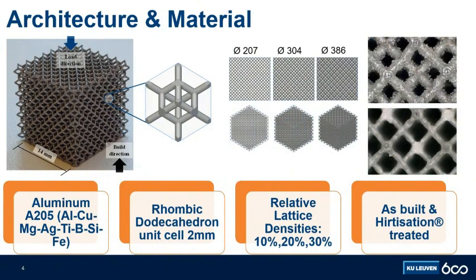For the architecture and the material, I have worked with aluminum A205. You can see the composition of the alloy on the screen. My main geometry was a rhombic dodecahedron unit cell of 2 millimeters, stacked horizontally and vertically 7 times to produce a cube with outer dimensions of 14 millimeters edge.